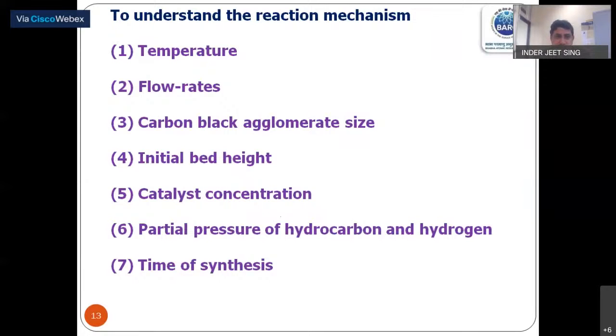After getting the temperature effect, there may be three different kinds of rate controlling step. One is external diffusion, another is internal diffusion, and the third may be chemical kinetics. To understand the external diffusion, we vary flow rates. To understand the internal diffusion, we vary carbon black agglomerate size and initial bed height. Catalyst concentration and partial pressure are varied to understand the effect of the chemical reaction controlling factor.